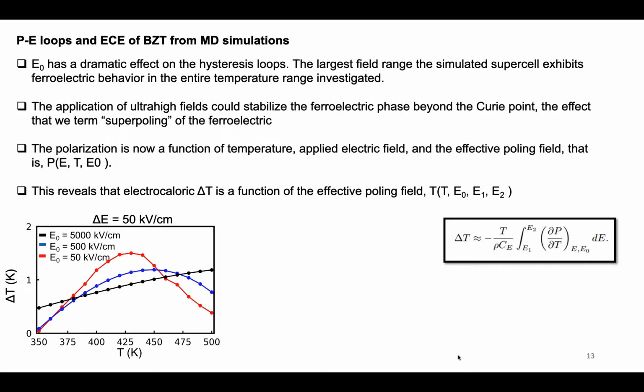So we think that this is a kind of variable that might be hidden in the electrocaloric effect, or might be in the caloric effects in the ferroelectrics. So we should give more emphasis to why there are so many discrepancies in the literature when we investigate the electrocaloric effects in materials, because reproducibility, as we know, is the biggest issue, and the poling field has been, I don't say neglected, but it has been overlooked. So that can act as one of the variables in the electrocaloric change in temperature.